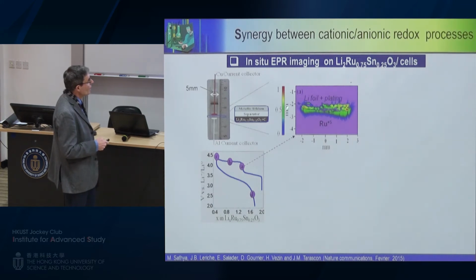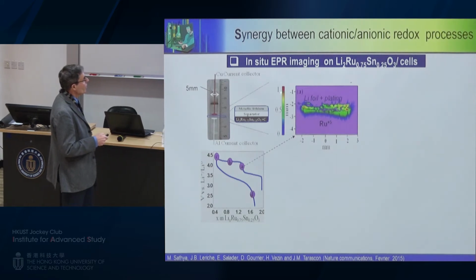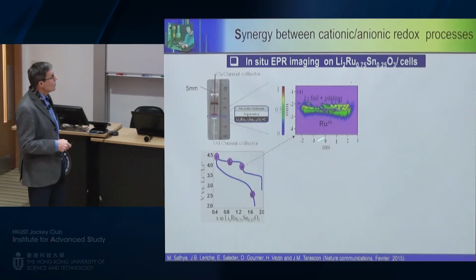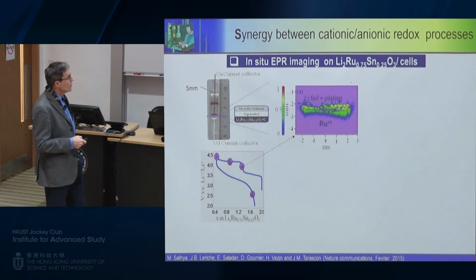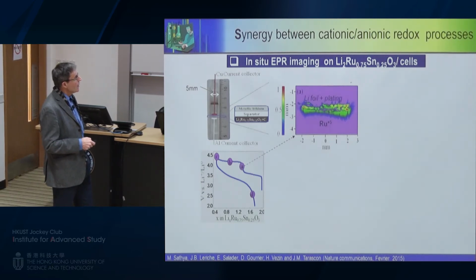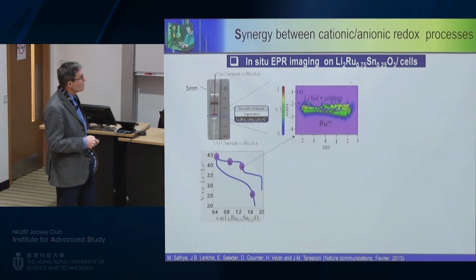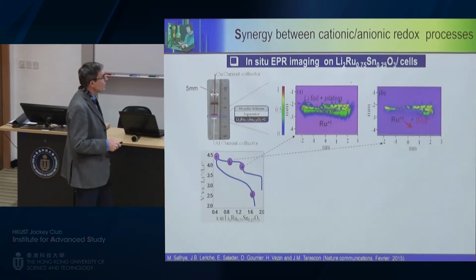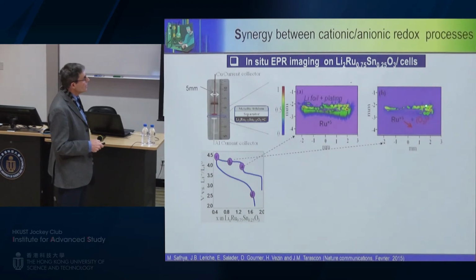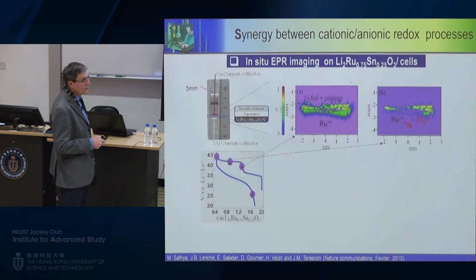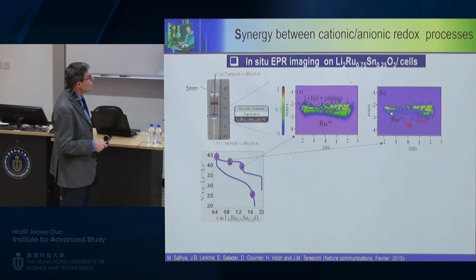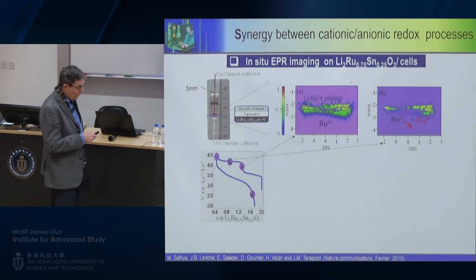And here I put a color bar to indicate the range of spin: blue, low; green, medium; and red, high density. Now you look at the compound when we are at this potential at 4 volts, you can see that both electrodes are green, associated on one side to the spin of lithium plating, while on the other side you have the ruthenium plus 5. Now, if I increase the potential, you can see I still have the spin at the negative electrode with some greenish part, whose high density indicates that some lithium is agglomerated. But look here, I have a disappearance of the spin at the positive electrode, which is consistent with the fact that we are at the transition from ruthenium plus 5 to a peroxo species.